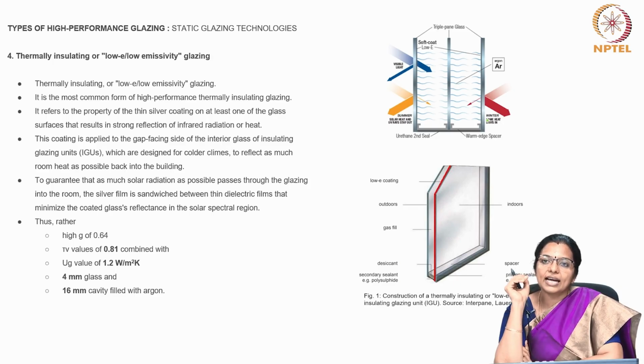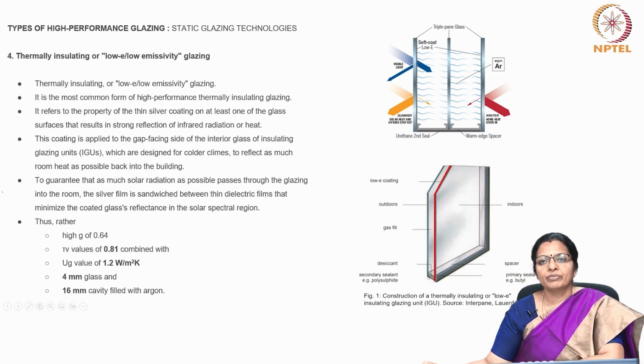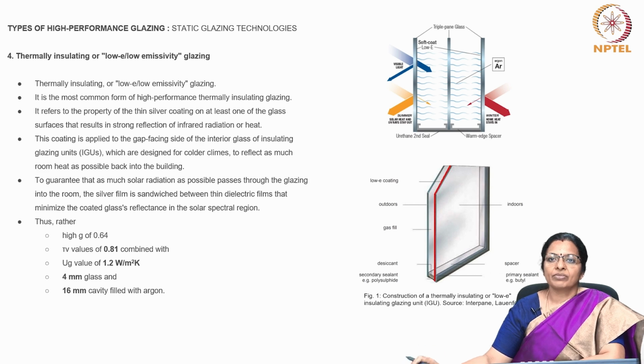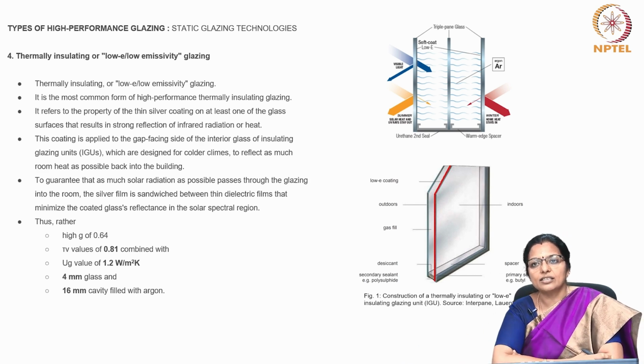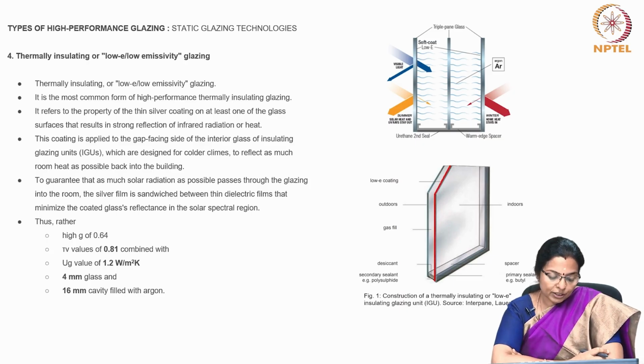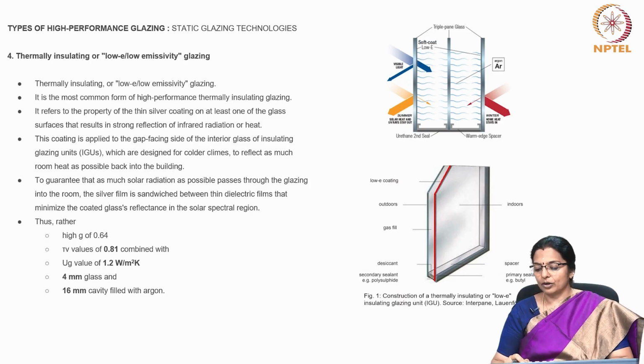To guarantee that as much solar radiation as possible passes through the glazing into the room, the silver film is sandwiched between thin dielectric films that minimize the coated glass's reflectance in the solar spectral region. Thus, a high g of 0.64 and a transmittance of 0.81, combined with a U value of 1.2 watts per meter square Kelvin for a 4 mm glass and 16 mm cavity filled with argon, can be obtained.